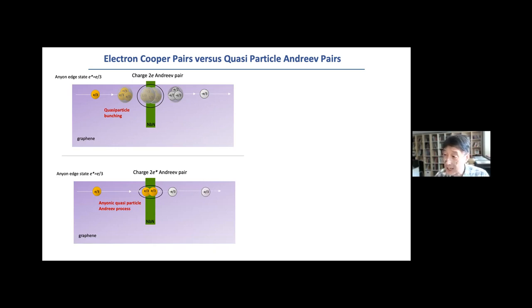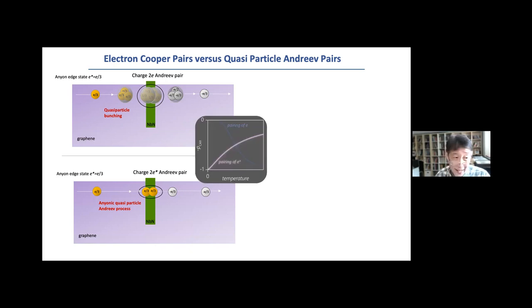In fact, the theoretical argument tells us that in the upper cases, charge 2E Andreev pairs, since you need a bunching process, it actually costs energy, which means that as you go to lower temperature, it tends to be suppressed, while for the charge 2E star Andreev process, there is no bunching needed. If this is indeed close to the ground state properties, you expect to see that stronger process happening at lower temperature. So temperature dependence may actually tell us these distinctions.